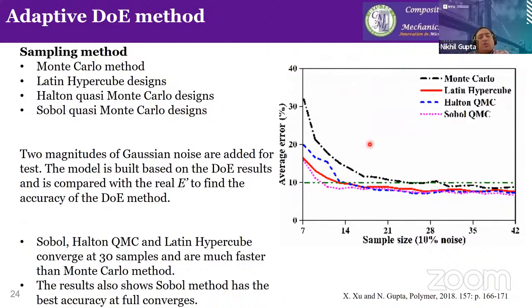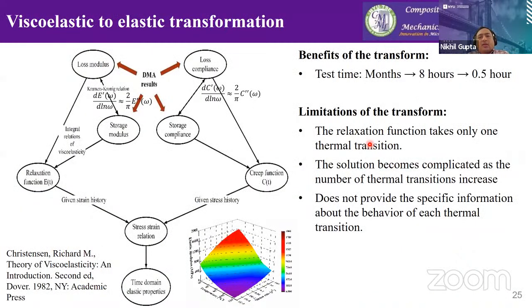And what it does is that if you have to measure only 10 combinations of temperatures and frequencies, in that case, the testing would take less than half an hour of machine time. And then you have the entire chart with about the same accuracy as you used to have from the tensile test. So what we were able to achieve in this case is that the months of testing was first reduced to 8 hours, and then we further reduced it to about half an hour, and that was quite useful.